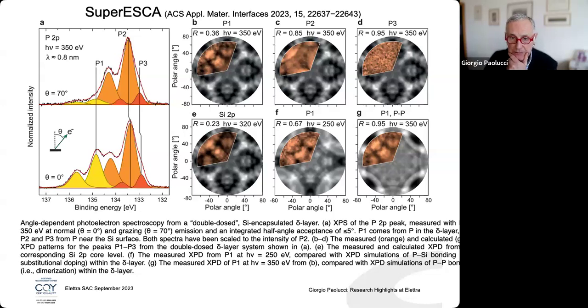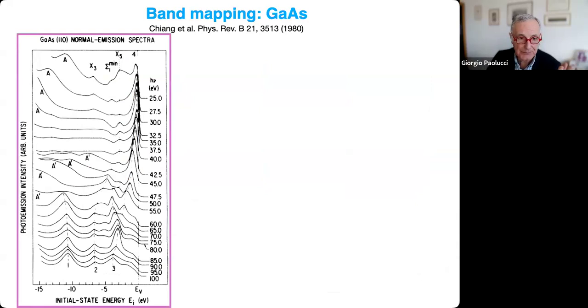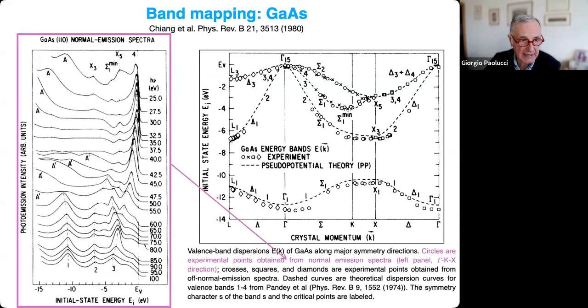The other thing that you can do is that you can apply all what we said to any kind of sample. So for example, if you look at one of the first things I showed you, this is a simple semiconductor that was done using variable photon energy, but of course you can look at a system of any complexity. So you can look at the evolution of band structure. Then you can identify, in any case, as I showed you in this alloy, if you are lucky enough that one of the atoms has the Cooper minimum, you remember that I showed you, here it is.